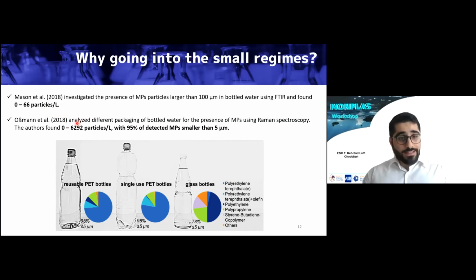In another study in the same year, the authors used Raman spectroscopy to analyze the plastic particles present in drinking and bottled water, and they found a range of 0 to 6,292 particles per liter. You can compare this number with 66 particles. And with 95% of detected microplastics smaller than 5 micron.